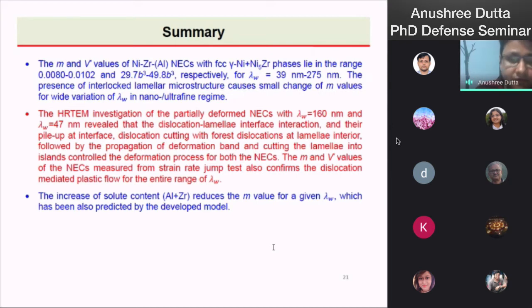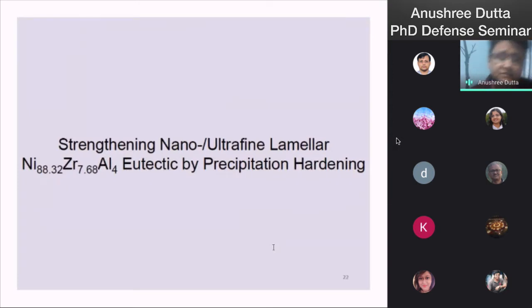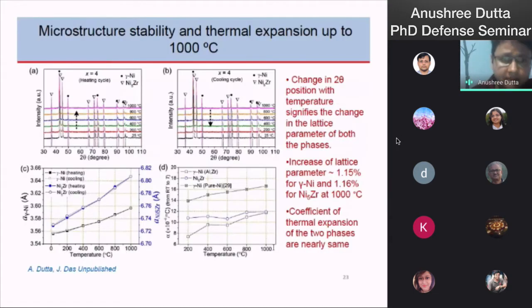The increase of solute content reduces the strain rate sensitivity value for a given lambda, which has also been predicted from the developed model. My third chapter is strengthening of nano ultrafine lamellar nickel 88.32, zirconium 7.68, aluminum 4 eutectic by precipitation hardening. In this slide, the X-ray diffraction pattern of the nano nickel, zirconium, aluminum is given.